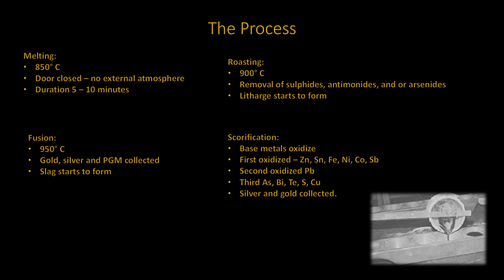All the base metals shown from zinc to antimony will oxidize first, in the order shown. Then the lead starts to oxidize into lead oxide. All those shown starting with the arsenic down to the copper will oxidize last. Some of these contaminants may still get trapped in the lead. Therefore, for full removal, a second scorification will be necessary.